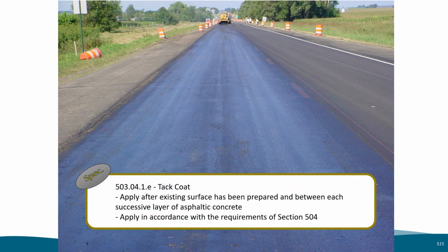As written in the standard specification, tack is applied after existing surfaces have been prepared and between each successive layer of asphaltic concrete. The tack will be applied in accordance with the requirements of Section 504. It is common for contractors to place tack far in advance, often a day ahead of laydown. This reduces waiting for the tack to break, increasing productivity. Visually confirm that the tack is ready to go.